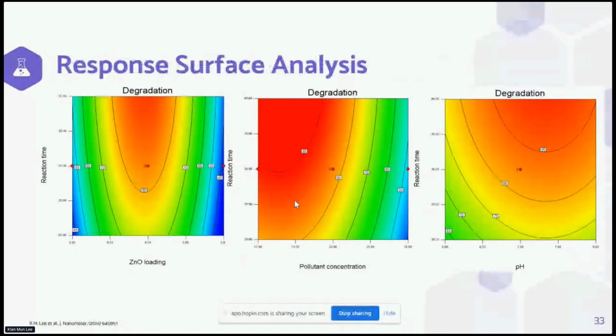The 2D contour plots show the interactive effects between reaction time with catalyst loading, with initial concentration, and with solution pH. What we get from these three figures is that the removal percentage increases with longer exposure duration to the UV irradiation, mainly because more photo-induced holes and hydroxyl radicals will be generated, which facilitates the degradation of the organic molecules.